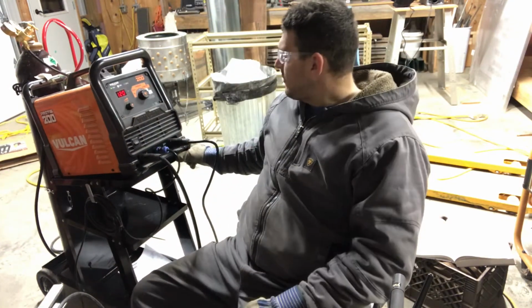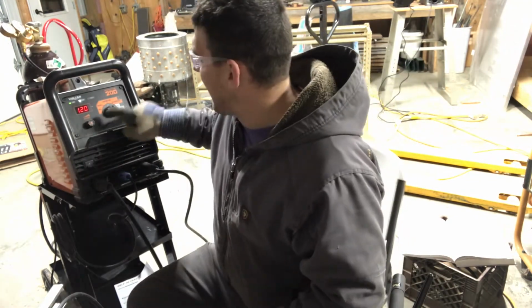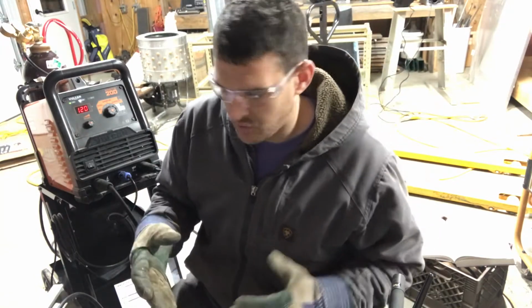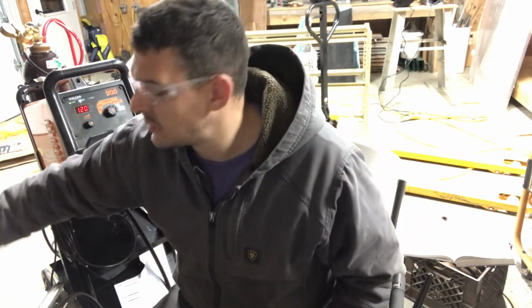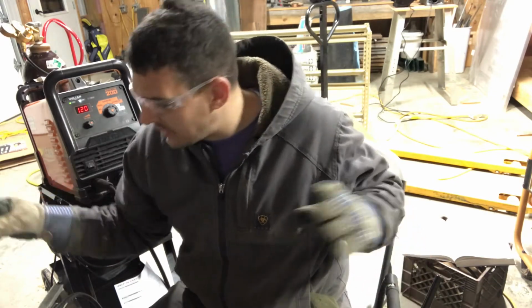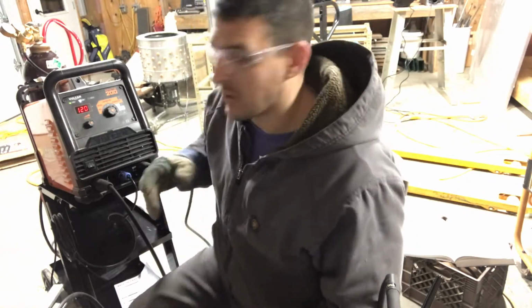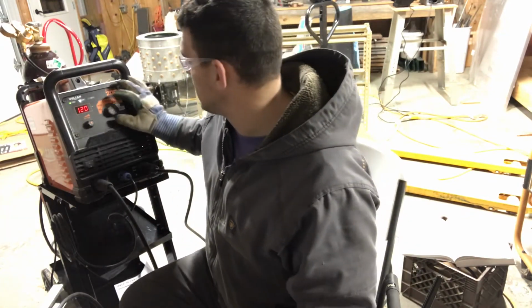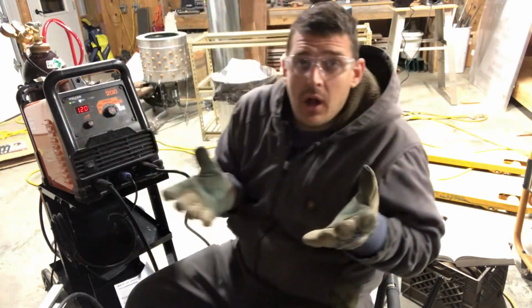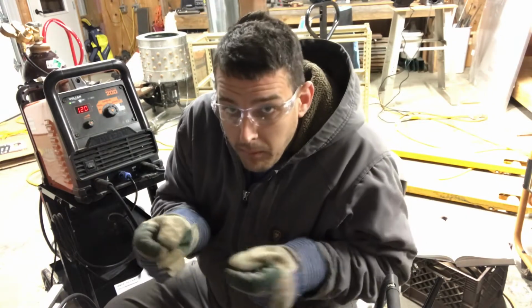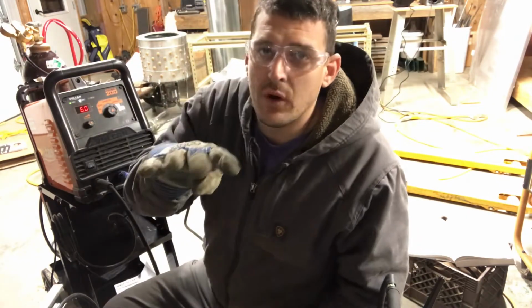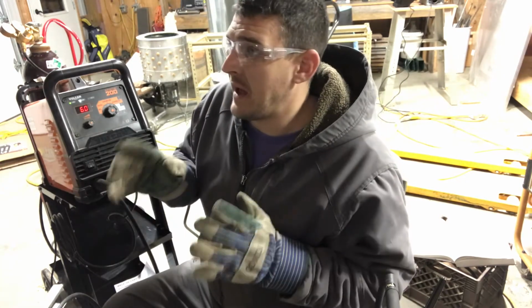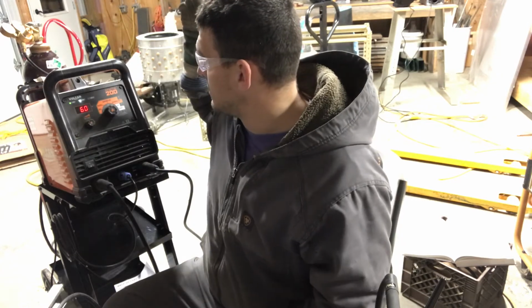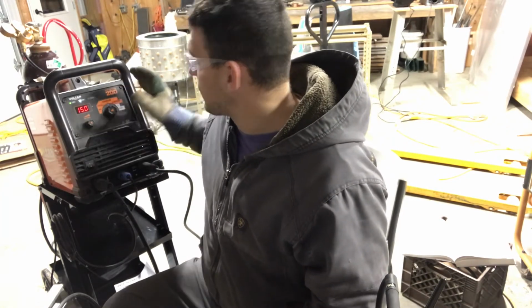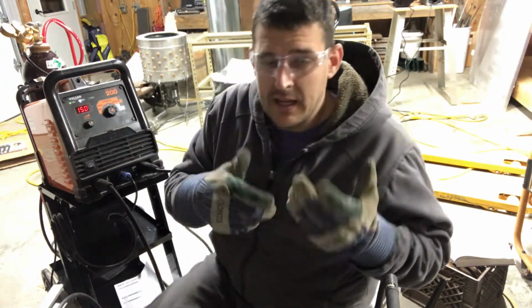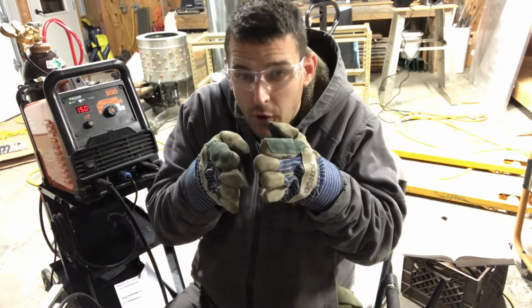So, my settings, if you can see: I'm going through 1/8 inch steel, doing a butt joint, and I'm using 3/32nd rod. I've got the 3/32nd tip, or electrode. I'm at 120 amps, which is maybe a little hot, but they say in welding, go hot, go fast. So I'm getting these better results. My AC balance, I've got 40% or 60% negative, so I'm at 40% cleaning and 60% penetration. My frequency, I've got full blast at 150, because I was reading online and in the textbook that the higher the frequency, the more focused the arc is.